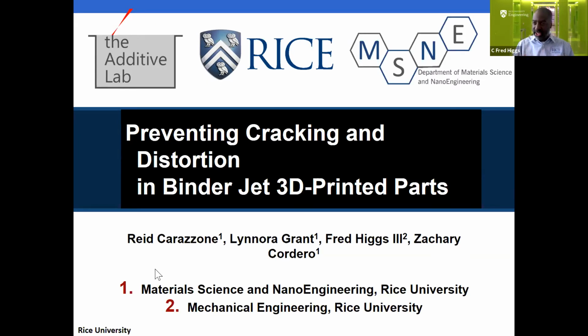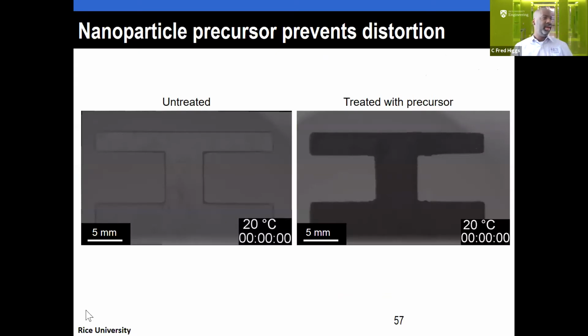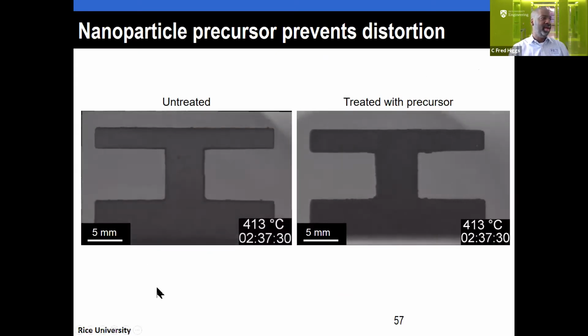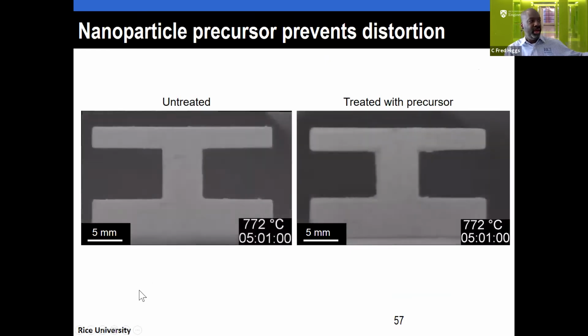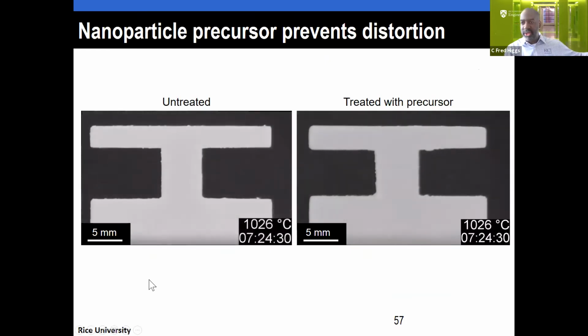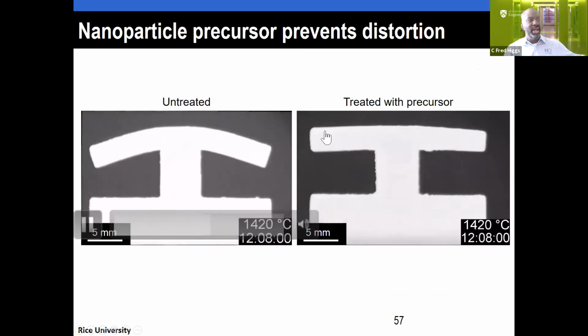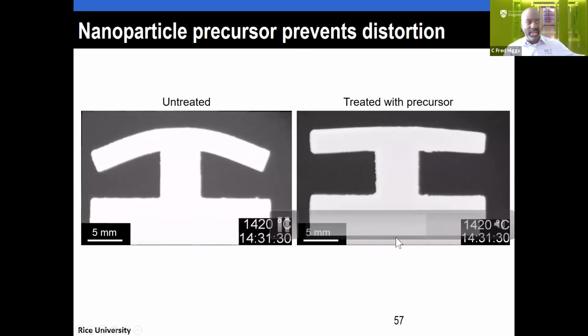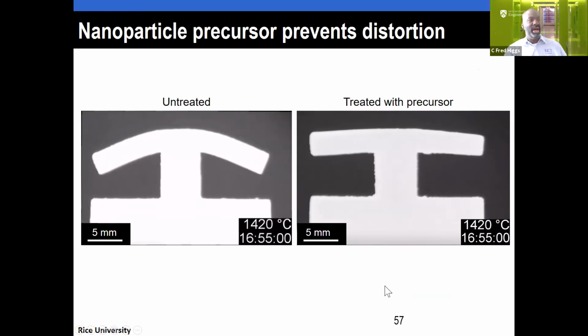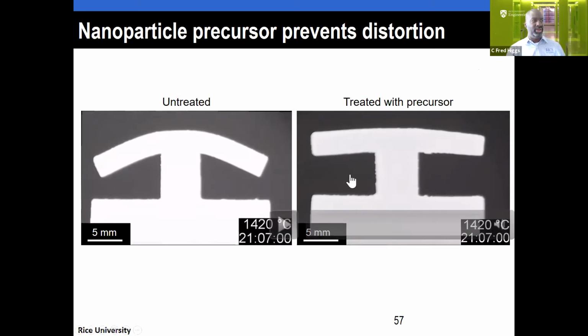Will that cut down on sintering? Because it turns out at the end of binder jetting, you have to heat up these systems and watch what happens to them. When you heat these up, you want them to become solid geometry that won't move. But the problem is that they distort. So here we use this precursor that we put in, a titanium dioxide precursor, and it formed these solid necks there, and it did reduce the distortion there.